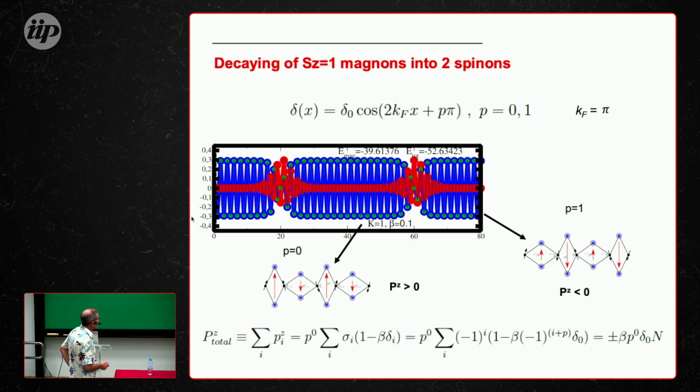And so when you create a magnon in the system, you will get a deformation that splits your original ground state into this. And what this picture means is that here you have one of the ground states and here you have the other one. Okay, so the system splits into two halves. I think I managed to put it here. So this region has this deformation where these guys pointing up got larger. So you will have a net polarization pointing out.